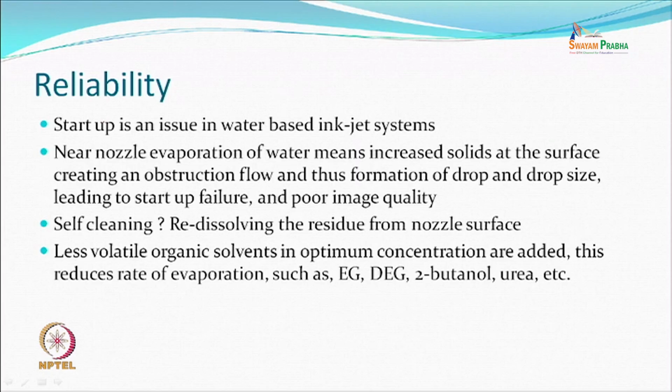So, less volatile organic solvents, we are comparing with obviously water, at some concentrations can reduce the rate of evaporation. Some examples, even ethylene glycol, diethylene glycol, butanols. In some sense they are water soluble, they are hydrophilic, they are not hydrophobic.